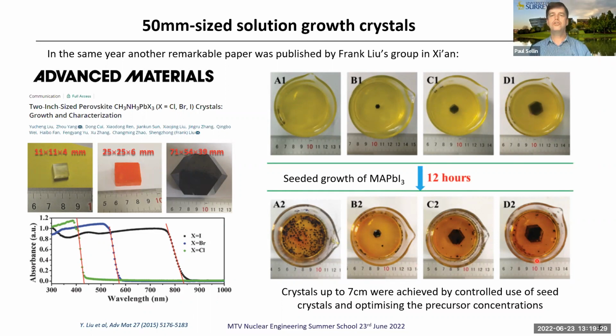And of course, the trick with this growth is optimizing the temperature ramping and the growth conditions to prevent spontaneous nucleation. You can see in picture A2, they're suffering a bit from spontaneous nucleation, where many crystals have started growing together. And that, of course, dilutes the growth away from one single site. Nevertheless, it's very nice, controlled growth.